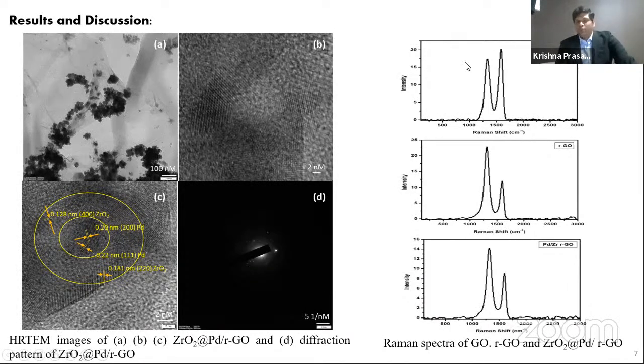And we have also recorded Raman spectroscopy to understand the defect nature of the reduced graphene oxide which has been synthesized, and we found that from graphite oxide to reduced graphite oxide, the amount of defects has increased greatly, and this in turn would help us in better anchoring the nanoparticles on the surface of the graphene. And that was the case even for PdZr RGO, which is the composite loaded graphene.